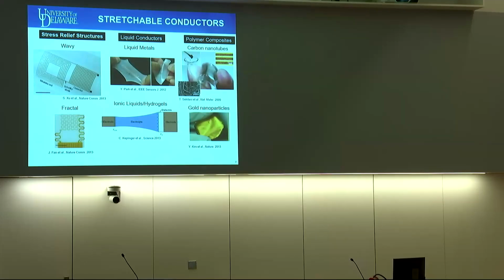Now, to make a stretchable electromagnet, to make a stretchable inductor, fundamentally, these devices are a coil of wire. And so as long as we can make the wire, the conductor itself stretchable, we can potentially make an inductor coil. And there's three main approaches that the community uses to make stretchable conductors, each of which have advantages and disadvantages. One of the more classic ones is to stir conductive particulate into an elastomeric material, which is very effective, but also has a relatively low conductivity. So something like many orders of magnitude lower than a traditional conductor like copper or silver.